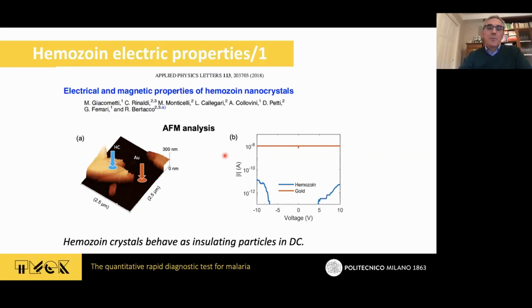This is a DC experiment in which we just put some nanocrystals of hemozoin on top of a gold-plated silicon substrate, and by using an AFM with a conductive tip, we measure the current flowing from the top toward the substrate in the case of a hemozoin crystal. And as you can see, we found that in a range between -5 and +5 volts, there is no current, within the limit of sensitivity of our amplifier. While in the case of the gold, you see that we are saturating at 10 nanoamps, which is really the saturation value of our amplifier. So the good news was that hemozoin crystals behave as insulating particles in DC, but this is not enough.